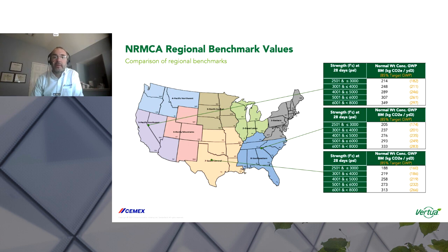So we can see over here on the West, for a 3,000 PSI concrete, the typical GWP is 248, but our target then would be 85% of that, which would be 211. Typically, as you look across this, there are some places where it's much easier. Typically in the South, especially like Florida, it's much easier to get low carbon concrete. They just have good aggregates. They get good strengths with a minimal amount of cement.